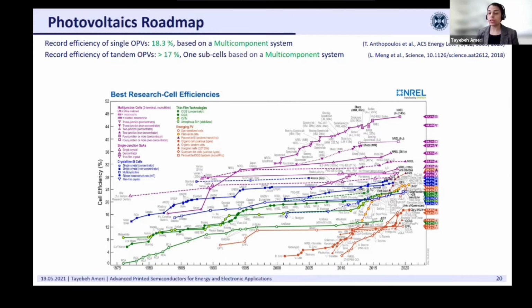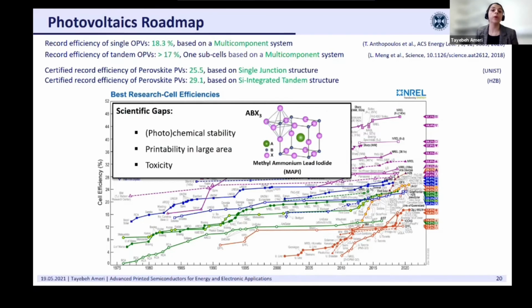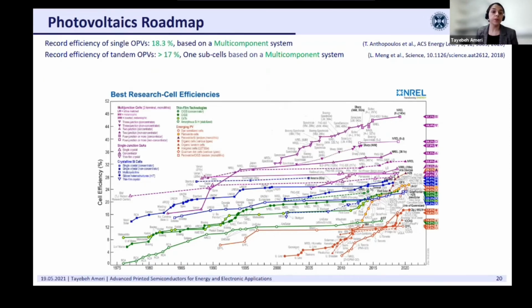However, in the meantime, a new technology also came up for photovoltaics, called perovskite solar cells, a crystalline material with the general structural formula ABX3. As you see here, this methylammonium lead iodide is one of the most reported and most efficient perovskite structures for photovoltaics. And in terms of performance, as you see here on this roadmap, they are achieving over 25%, which is indeed comparable with single crystalline silicon.